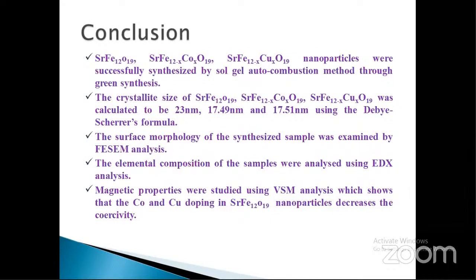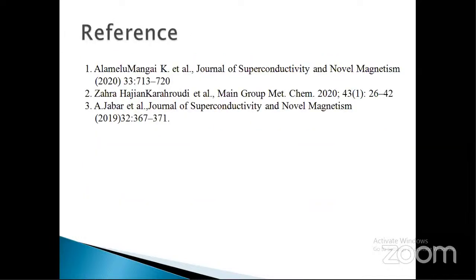So if the coercivity decreases, the loss will be low, and during operation the hysteresis loss will be less, so the life cycle of the refrigerator can be increased. Further, the decrease in coercivity should be tuned by doping, by varying the doping concentration. That has to be done. And further, the RCP values and magnetic entropy change should be calculated in order to calculate the efficiency of the magnetic refrigeration.